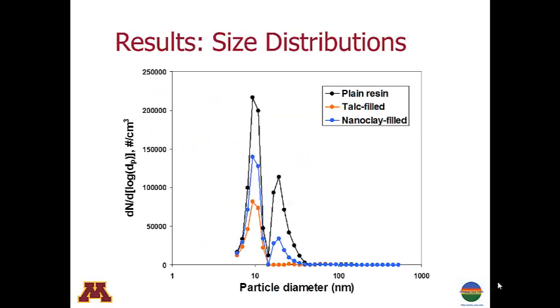This figure shows the frequency distribution measured by the fast mobility particle sizer for each of the test resins as a function of particle diameter on the horizontal axis. As we saw in the concentration measurement results previously, the plain resin in black exhibits the highest frequency distribution, followed by the nanocomposite resin in blue, and then the talc-filled conventional resin in orange. In particular, the highest points in the distributions are for particles about 10 nanometers in diameter and smaller.